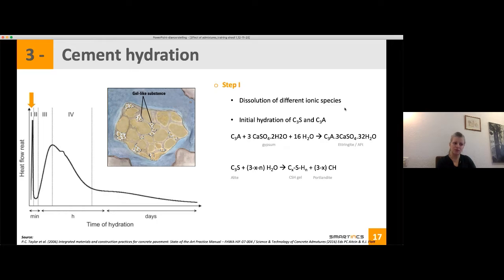And then at the same time, you will start to have dissolution of your tricalcium silicate to form a CSH gel and some portlandite. But the CSH gel that you see here, it's really a jelly structure and not yet the structure that you will have as CSH in a concrete. But what does it mean? So you will have some hydrates that are immediately formed, and it will cover the surface of your cement particles. So which means it will also be like a barrier so that you cannot have further reaction.